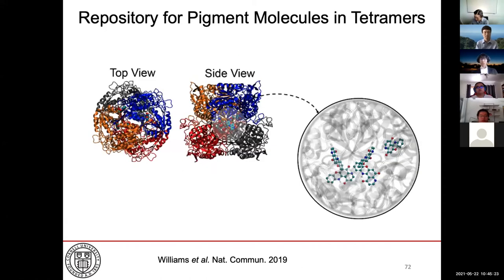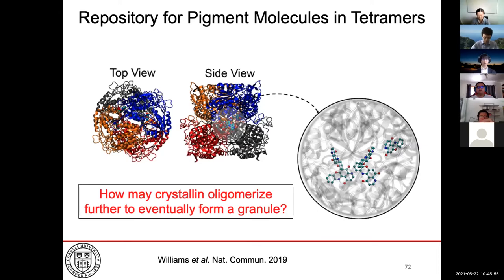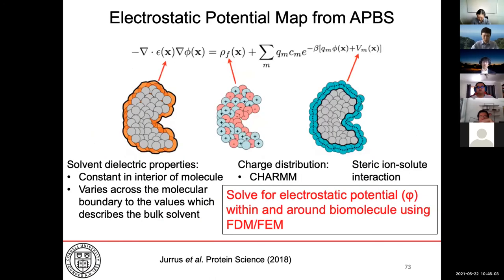The possible role of crystallin as a good pigment repository is further reinforced by the fact that they are very similar to a class of proteins known as aldehyde dehydrogenases, which are able to form higher order structures such as tetramers. So if we were to construct tetramers of crystallin and perform the same docking, an even greater amount of pigment molecules can potentially be stored within the crystallin tetramer. So we can clearly see the importance of crystallin localizing only in the pigment granules. And therefore, we would like to ask one more question. How may crystallin oligomerize further to eventually form a granule? To identify possible mechanisms for crystallin aggregation, I mapped the electrostatic surface of the crystallin tetramer using finite element methods, which account for solvent effects, charge distribution, as well as steric interactions.